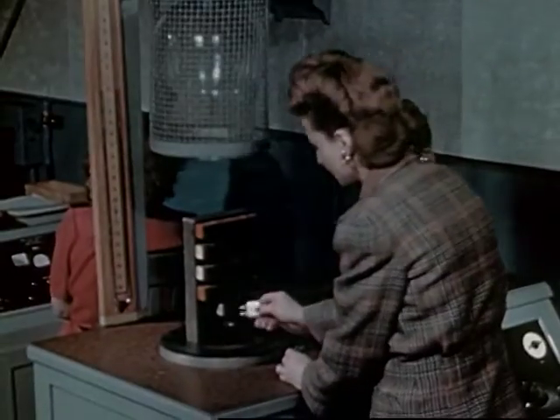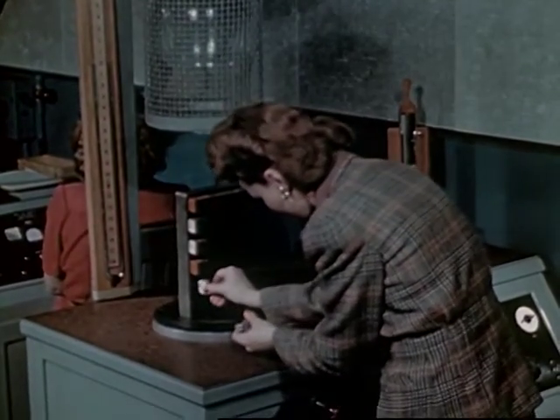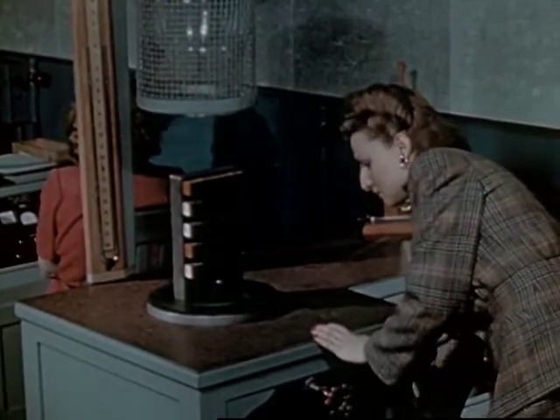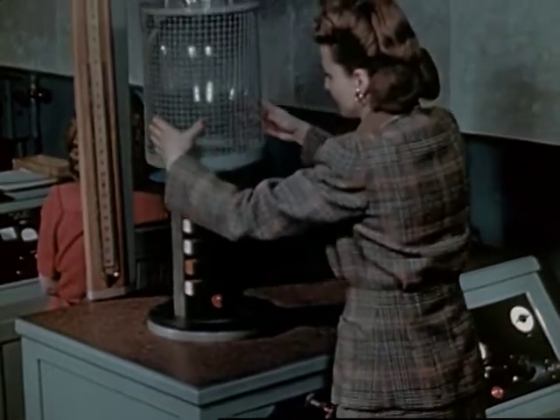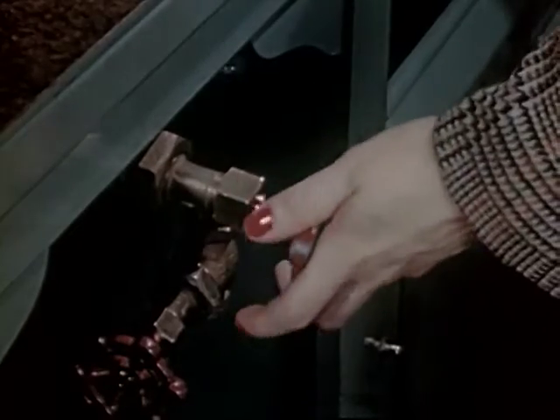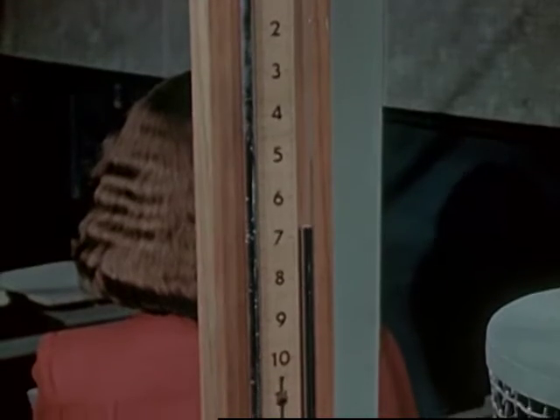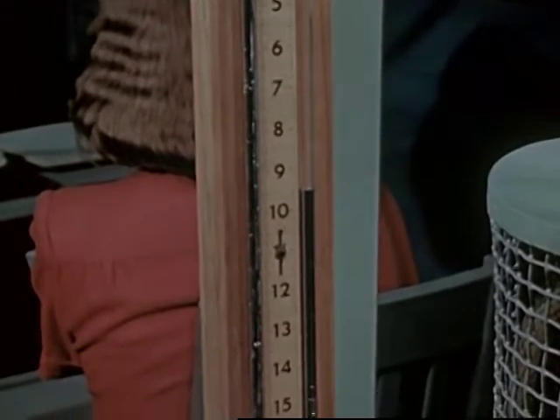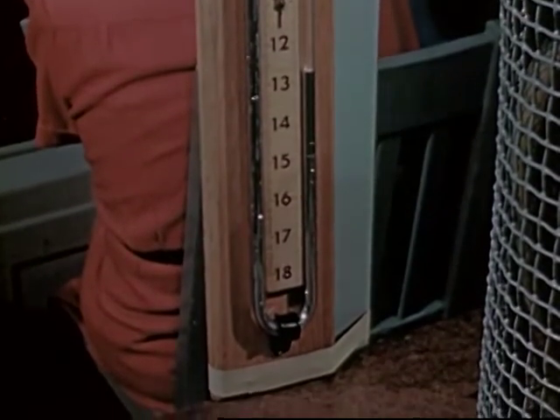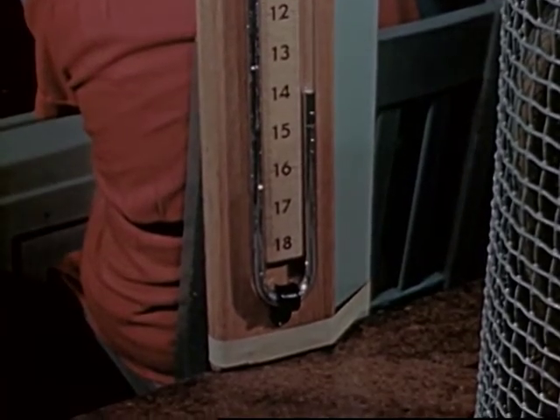At the completion of the temperature test, a final production test is made to see that the holder is tightly sealed against leakage. The crystals are plugged in groups of 60 into a rack which is enclosed in a glass vacuum chamber covered with wire mesh for protection. The air is pumped out as shown by the changing level of the mercury manometer. A potential difference of more than 1,000 volts is placed across the electrodes. If the holder leaks, an ionization current registers on the dial.